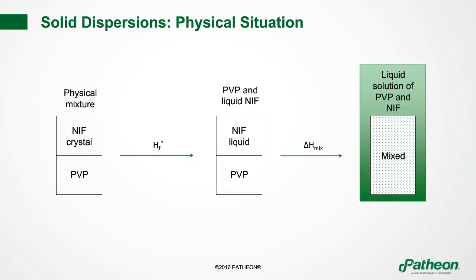So initially what you can look at is a physical mixture of pure crystalline drug and the polymer of choice. In this case, we're talking about nifedipine. That's what the NIF stands for. So nifedipine is the drug, and PVP is just polyvinyl pyrrolidone. Initially, we take the nifedipine crystal and the polyvinyl pyrrolidone powder, and we crush them up with mortar and pestle, if you will, and make a physical mixture of them. But they're not intimately mixed at that point. You still have microcrystals or nanocrystals of nifedipine in a physical mixture with PVP.